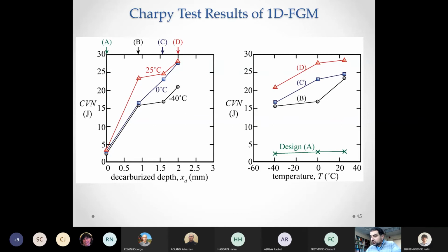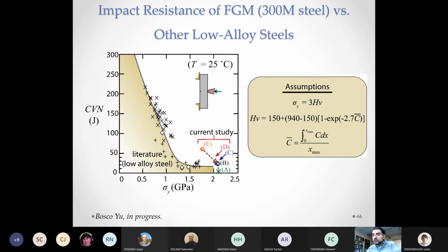And I won't go too much into the details here. I'll just show you the big picture here, where if we plot the general trend for the Charpy impact versus the yield strength, there is a trade-off. As the yield strength increases, the impact toughness decreases. And in fact, initially our material follows this trend, but the more we decarburize it, the more we can break away from this trend and achieve a new combination of strength with improved impact toughness by decarburization.